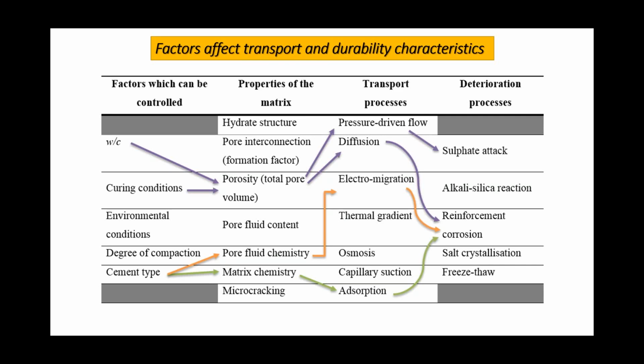So one of them is diffusion, one of them is permeation, the other one electromigration, absorption, and so on and so forth. But all of this can create a pathway inside the concrete, and this pathway may end up degrading our material. We also have some deterioration processes inside the concrete, which I mentioned: reinforcement corrosion, which is the major one, and also sulfate attack, alkali silica reaction, and also freeze and thaw. But I'm going to quickly go and explain these major deterioration processes inside the concrete.